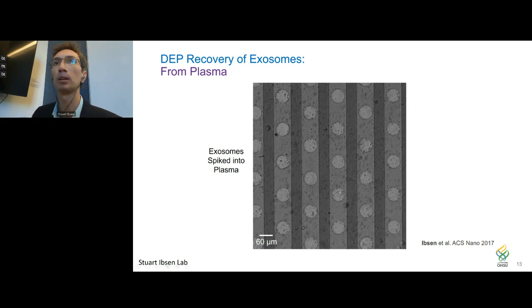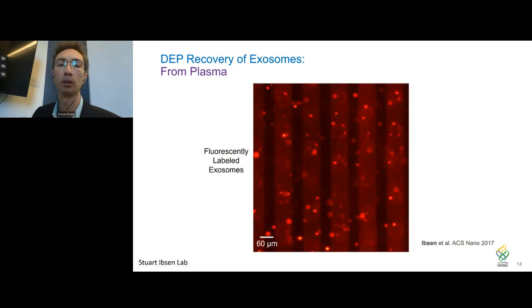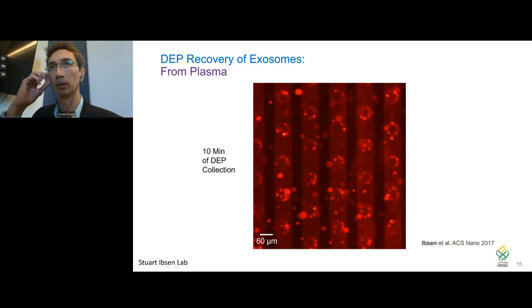And when we look at things under fluorescence, we actually see that the particles are really well distributed throughout the entire sample. So with 10 minutes of applying that alternating field to the electrode array, we see really good accumulation of the particles around the edge of the electrode, good accumulation. And then we do a 10-minute wash and purify these particles.